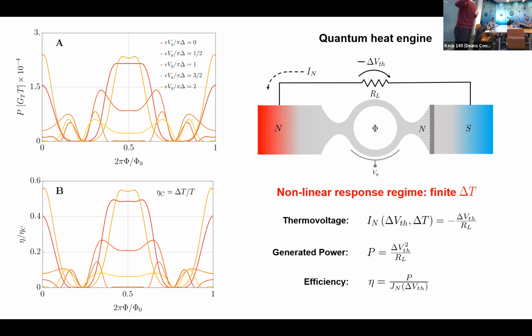At least in principle, you can notice that the phase and the electrostatic potential act in two different ways, because the phase lets you acquire plus phi if you're going in one direction and minus phi if you're going in the other direction. So it's a collective phase. Vg instead is just acquired on one arm, so it does not depend on the differential mode. They act differently on your system, and you can tune these two quantities to enhance your figure of merit. Here it is the power, for example, but you can also tune the efficiency, and it's really parameter dependent.